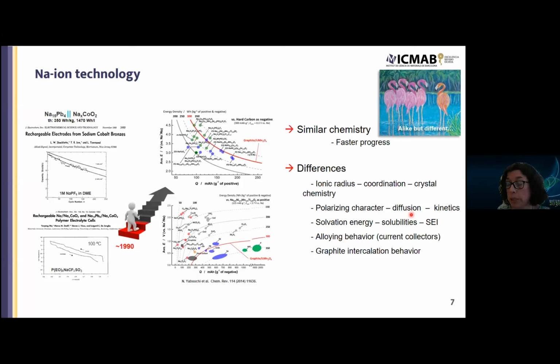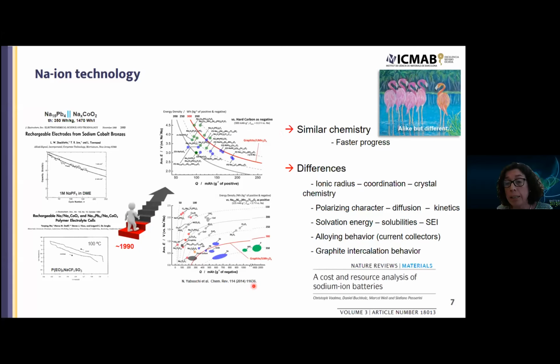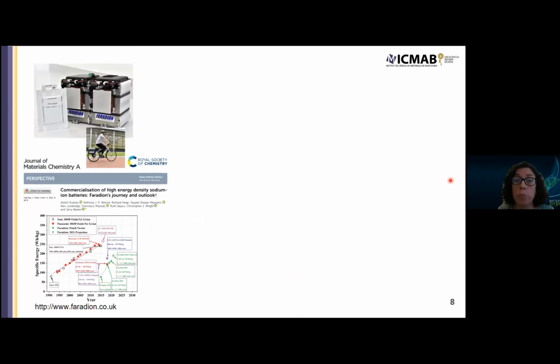Alloying behavior is different, and that's why sodium does not form alloys with copper electrochemically, and aluminum current collector can be used in both electrodes in sodium-ion technology, which is an advantage. And another significant difference is that graphite does not intercalate sodium, or at least unsolvated sodium, and typically hard carbon is used instead. And I would like to redirect you to this paper where there is really a nice cost and resource analysis for sodium-ion technologies, and figures and numbers are put into these ideas, and this will give you really an idea of how the technology has been progressing.